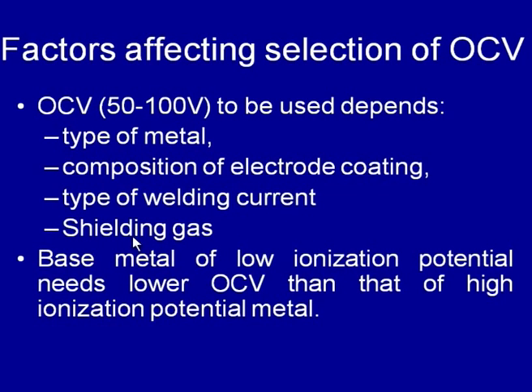Shielding gas also affects the selection of the open circuit voltage, because gases like helium, which have a higher ionization potential, require a higher open circuit voltage than other shielding gases. So, the selection of the shielding gas, the type of welding current, the composition of the electrode coating and the type of metal to be welded affect the optimum setting of the open circuit voltage, and it must be chosen properly so that it is neither too high nor too low, because too high an open circuit voltage will tend to give a shock, while too low an open circuit voltage will have the tendency to get the arc extinguished. So, to avoid any extinguishing of the arc, the lower side open circuit voltage should not be too low.